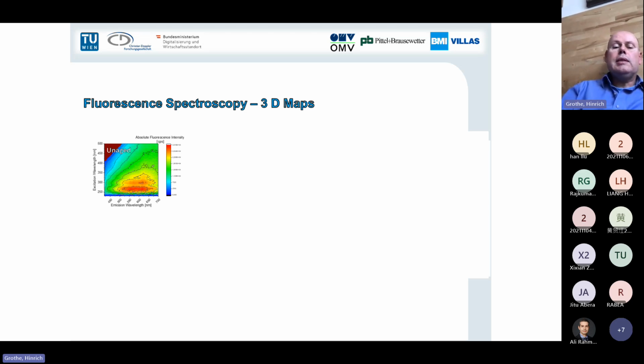And we can also see the differences here. The upper one, this is the pressure aging vessel test. So this is a conventional technique. Then we have the Vienna binder aging, and it is different to what you observe with the PAV. And then you see what we had from the field aging, so from this road really taken, the 17 years old sample. And that comes much more next to the VB aging than the pressure aging vessel test.